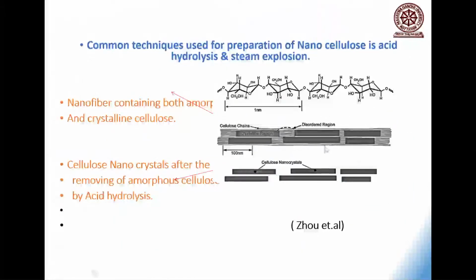And dear students, this is long nanofibers where you have amorphous and crystalline entities. You can see this is the disordered region. If you use a strong acid, you get short nanocrystals because strong acid can destroy all the amorphous part. So you have two options. You can make long nanofibers, the length could be several micrometers, or short nanocrystals, length could be around 150 or 200 nanometers. The diameter is always in the range of 20 to 50 nanometers.